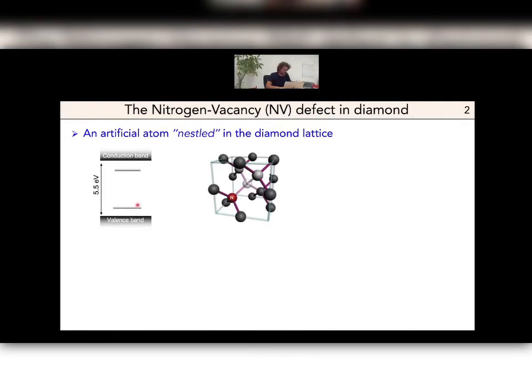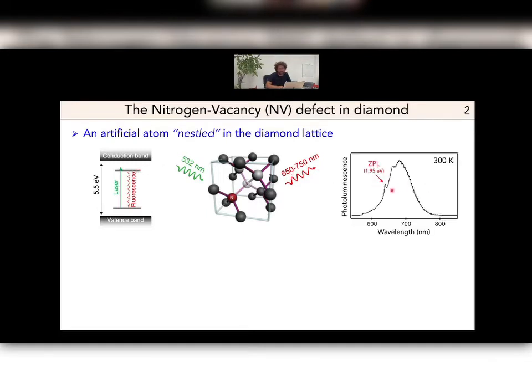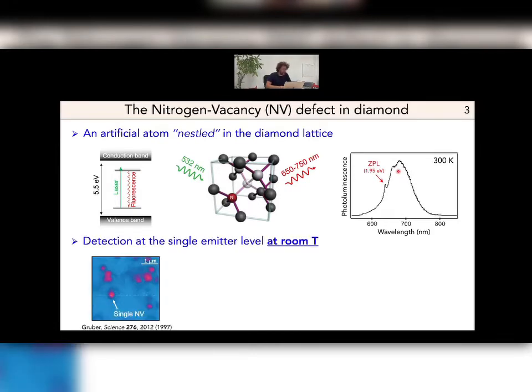This defect is optically active, so you can excite it with a green laser and you will collect some photoluminescence with a very broad spectrum, centered around 700 nanometers. So this defect has been known for more than 50 years, but it was only in 1997 that it was detected at the single emitter level at room temperature.